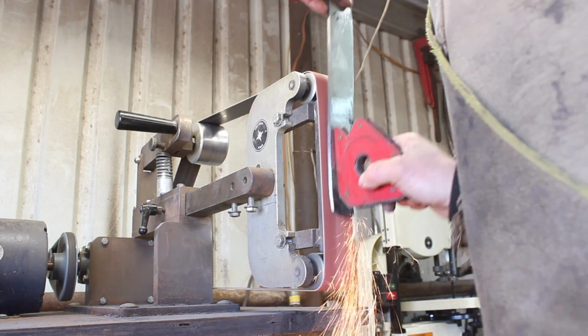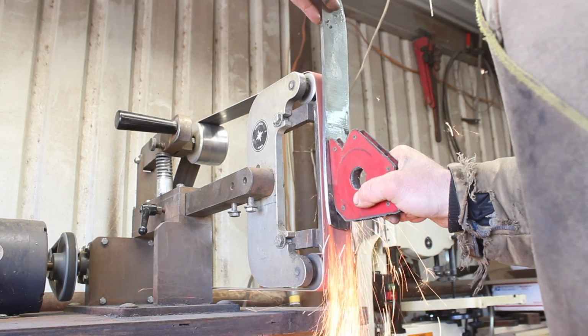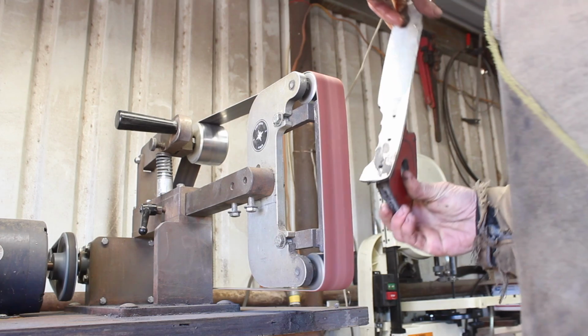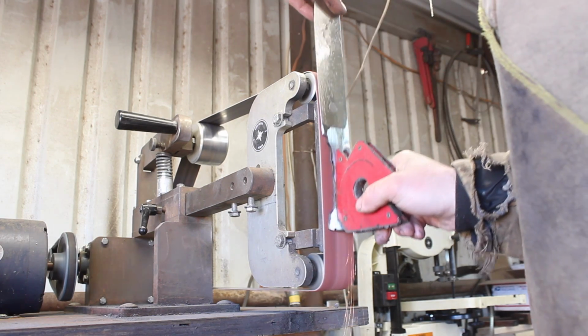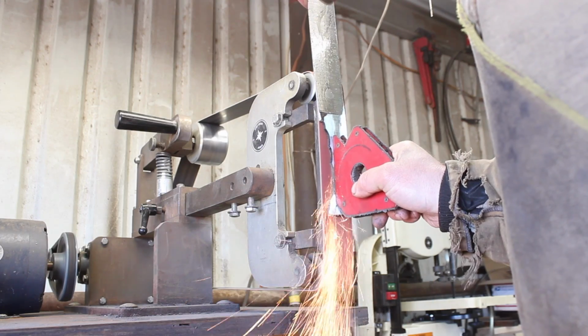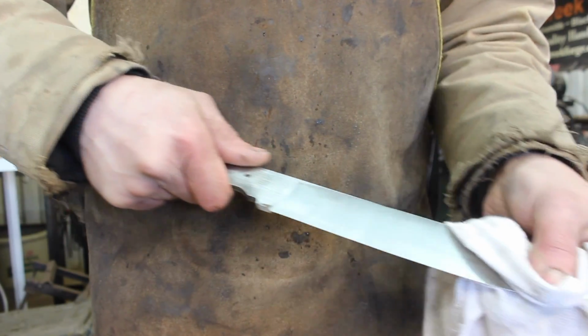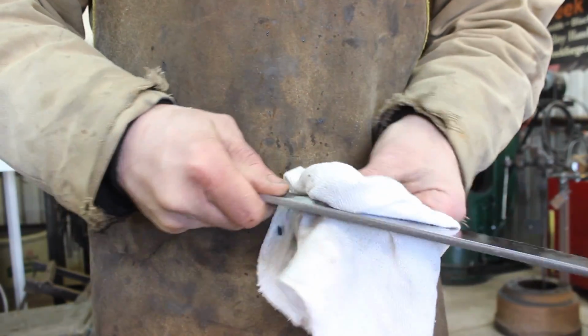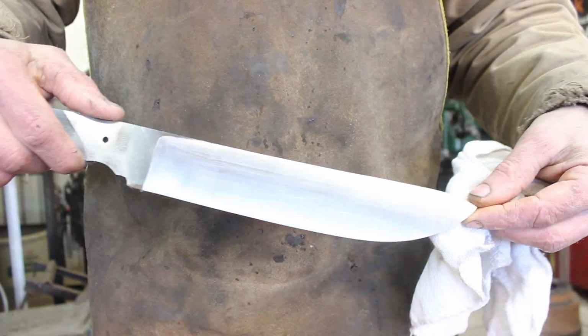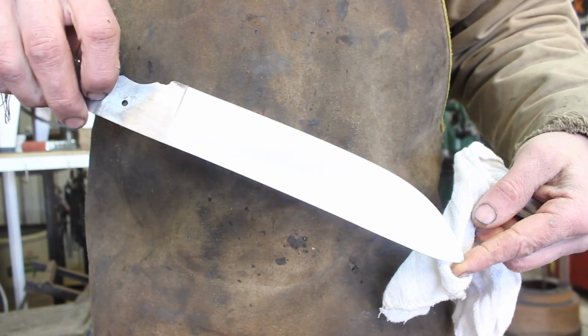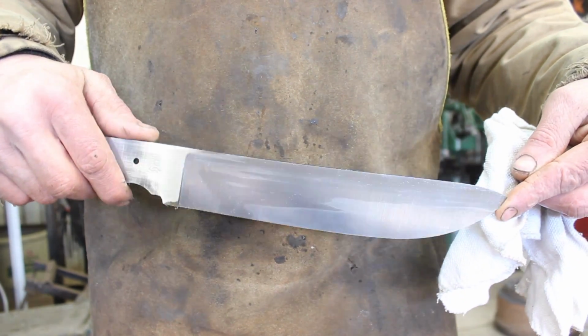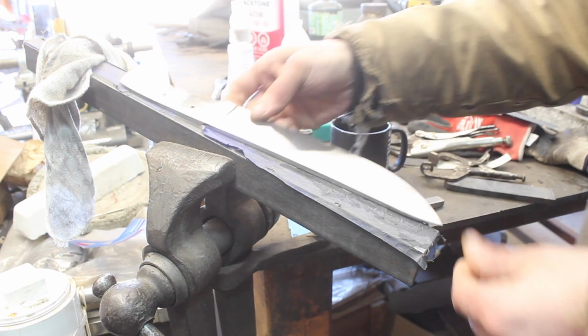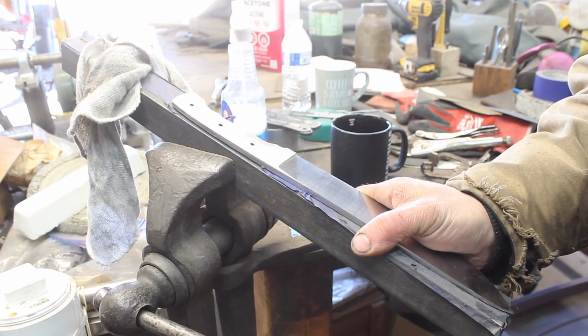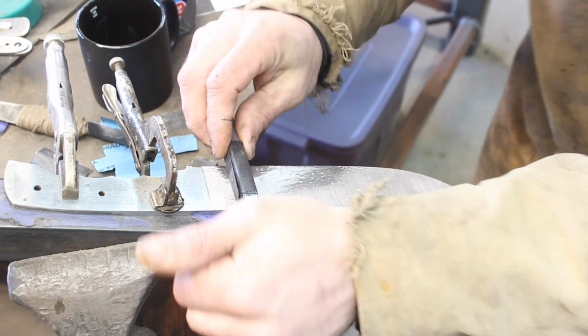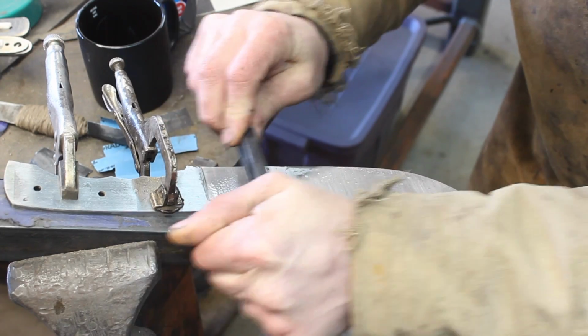You have to grind your bevels to an invisible point, an invisible reference point, if you want your edge steel to be centered in your blade, which of course we do. But anyway, at this point I've got it finished ground, and I'm really liking the appearance of the blade. Very clean welds, very clean piece of steel, solid, no inclusions, no voids, no anything at all. What you're seeing there appears to be a solid mono steel. It is solid, but it appears to be just originally one piece of steel, which is what you want.